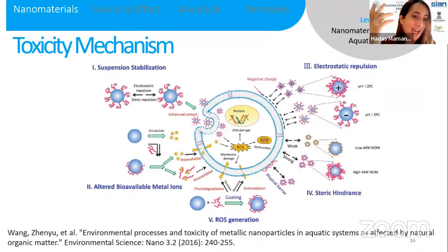When we coat a membrane with N-doped titanium dioxide and expose it to solar radiation, we form hydroxyl radicals. Now, we wanted the hydroxyl radicals to oxidize the virus exterior components, okay? But what happened is that we had calcium in the water, and the calcium actually served as a bridge between the membrane and the virus.